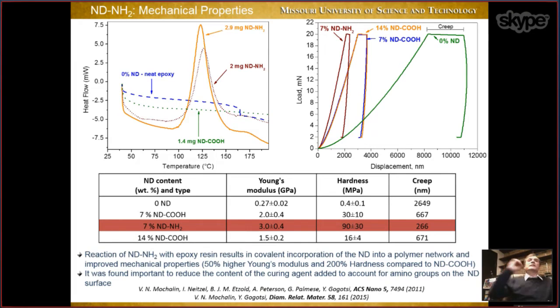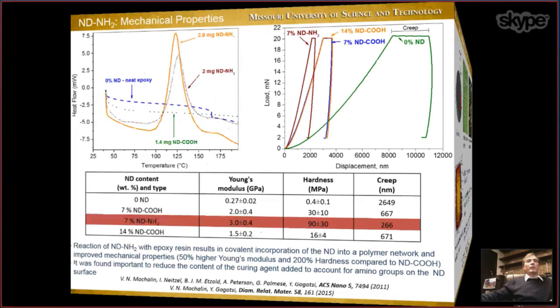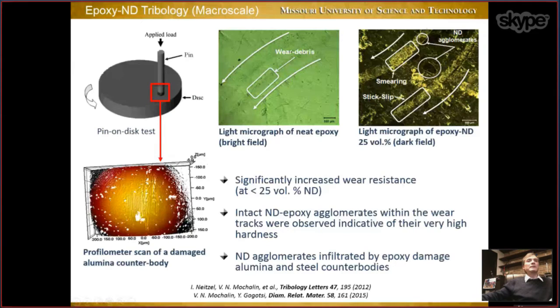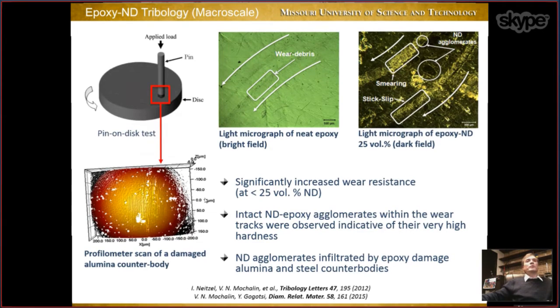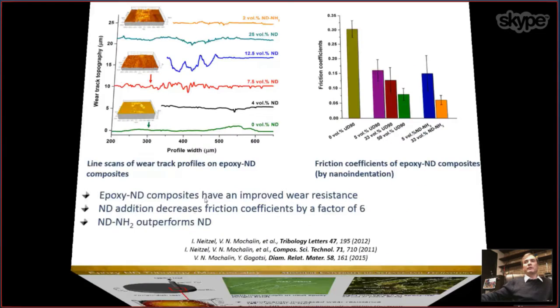Okay, so of course these composites show very high mechanical properties in other tests. For example, the epoxy nanodiamond composite can scratch the surface of alumina, which is a very hard material. Can you imagine polymer? Epoxy is polymer, right? So polymer with nanodiamond scratches the surface of alumina, which is very hard. It also has very low friction coefficient, as shown here.